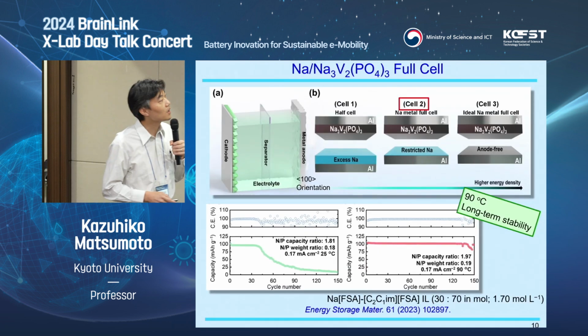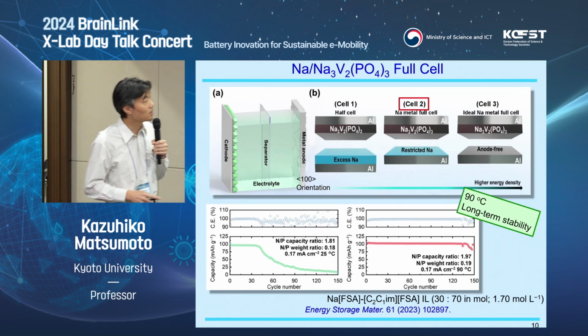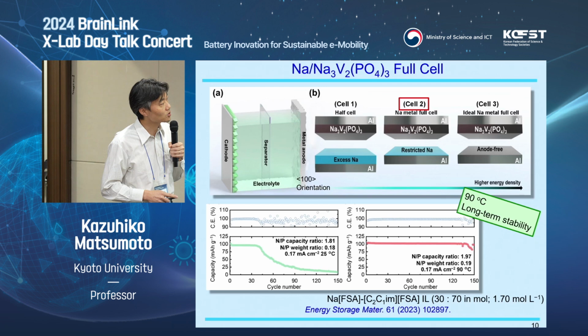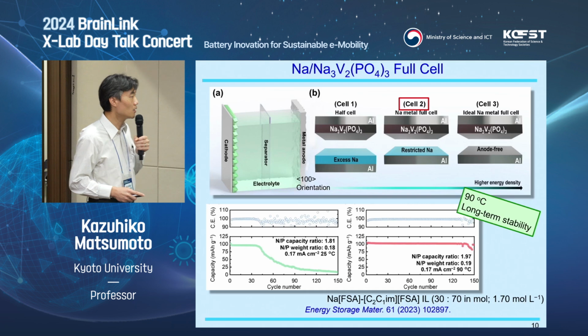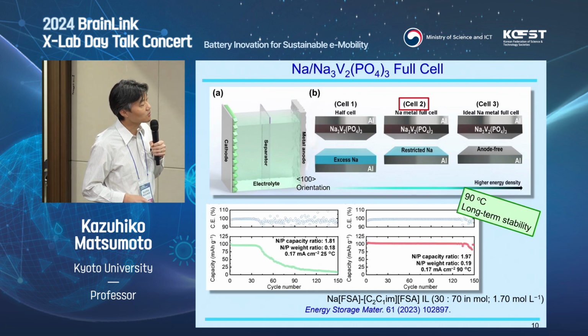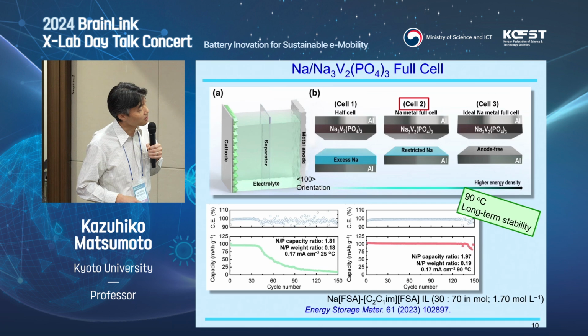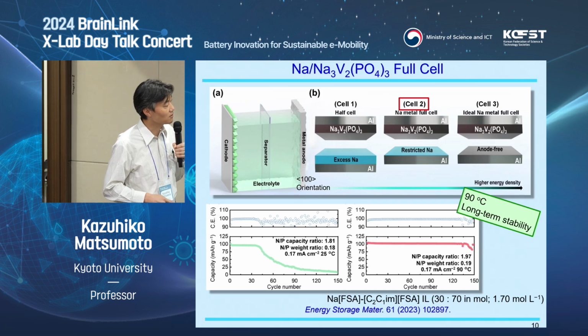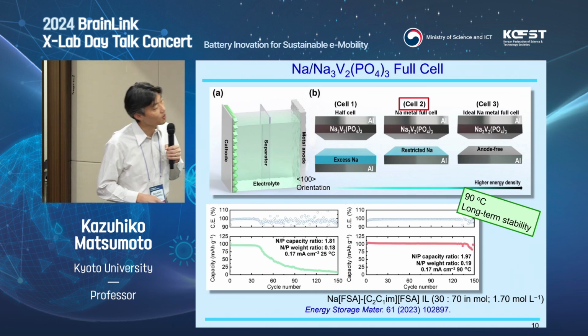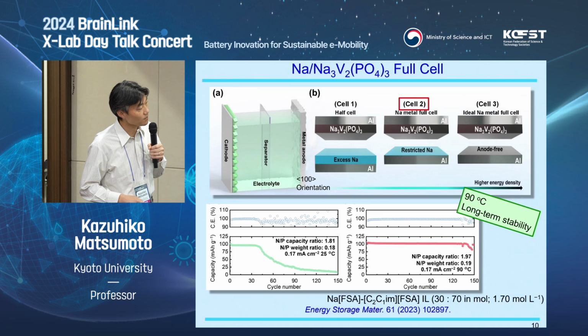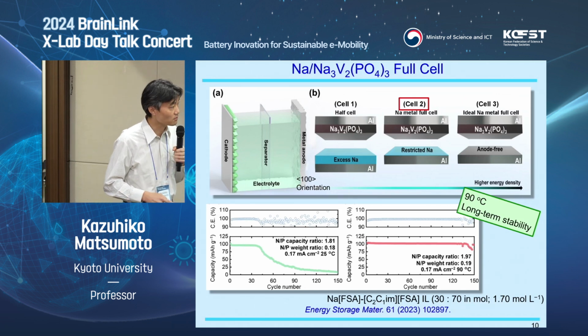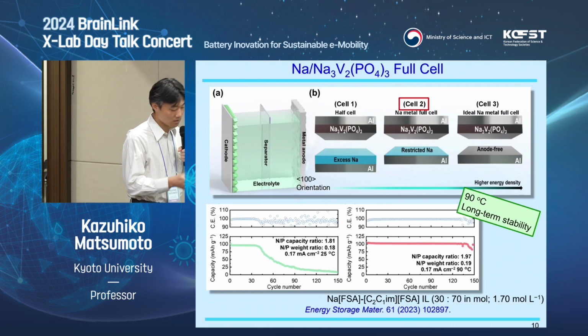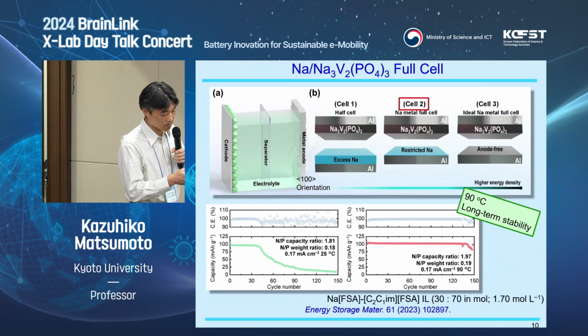So based on these data, we made a sodium NASICON full cell. Typically, when we measure the performance of positive electrode, we make a half cell with excess sodium metal. But in this case, we put only a restricted amount of sodium metal on the negative electrode. So in this case, the negative to positive capacity ratio equals 2. And then we did the full cell test. The left-hand side is again 25 degrees C, and the cell capacity decreases after 30 cycles. But at 90 degrees C, in the same condition, the capacity is kept over 120 cycles. So obviously, the sodium metal deposition actually controls the performance of this type of full cell.